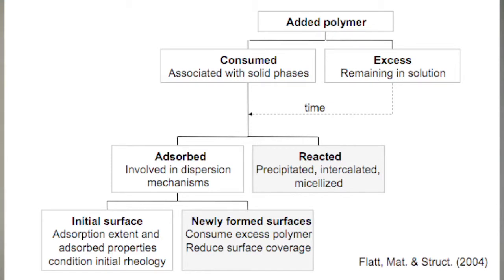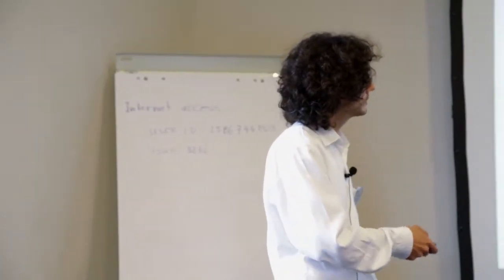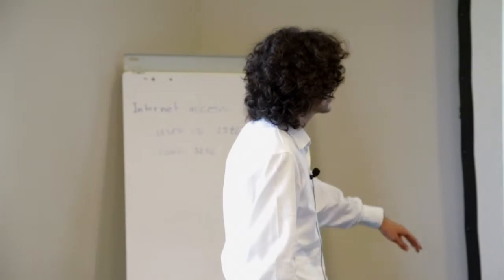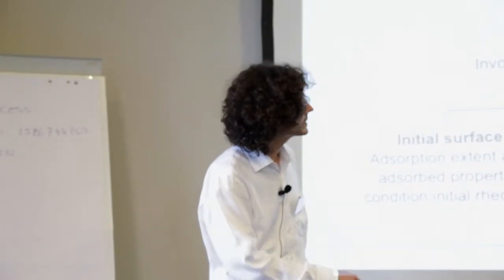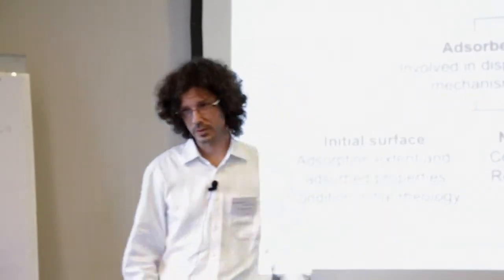It all roughly still fits into this picture that I proposed some number of years ago, where you have polymer added, divided between a consumed part and an excess part remaining in solution, a part adsorbed, which is relevant to dispersion, and this relating to the initial surface, adsorption extent and amount, conformation dictating the rheology. But part of the material might be lost, and over time, probably very quickly in the first stages of hydration, we have formation of additional surfaces which consume part of the excess and therefore perturb the time evolution of the superplasticizer's efficiency. So with this, I think my time is up.